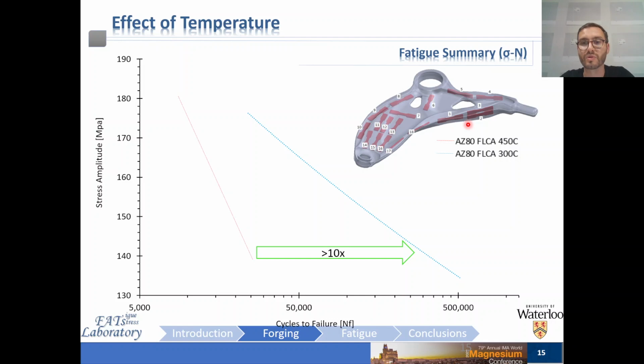The effect of processing temperature is really important in the last step of the thermal history prior to the in-service use, i.e., it isn't the extrusion temperature, but the die forging temperature and subsequent cooling schedule that you use following the forging process that governs the final microstructure that you end up with in the forged component. Although we did look at some post-forging heat treatments in this project, I've chosen not to discuss them here as they're very alloy and application specific. You can simply think of the analogy that the final heat treatment will govern the resulting microstructure, precipitate content, and morphology of those precipitates, as well as the properties. If no specific heat treatment is given in the last step of the thermal history during the forging process, that's what will be replacing it.